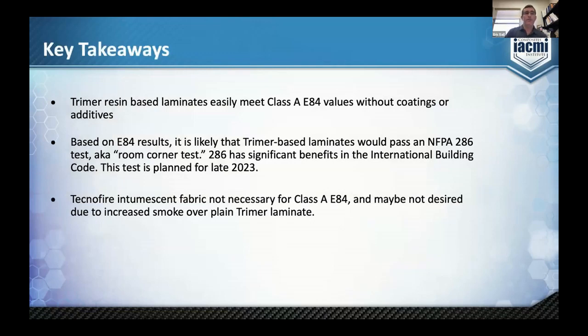So, kind of key takeaways for this: trimer resin based laminates easily will pass a Class A E84 without coatings or additives. Something we're going to be looking at is doing an NFPA 286 test, aka the room corner test. We believe it will pass very easily without any kind of coatings, and this test is planned for later this year. The Tecnofire intumescent fabric is not necessary for the E84 surface burn, because the trimer does a great job without any intumescent.